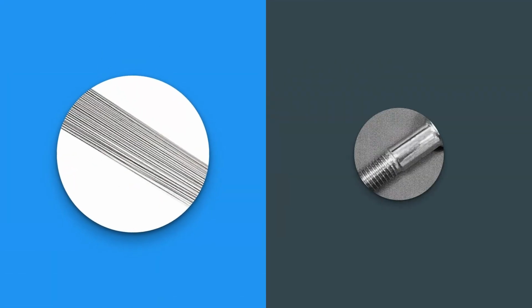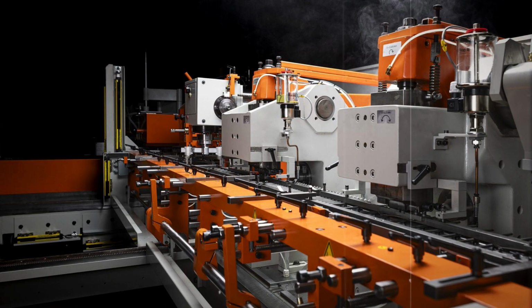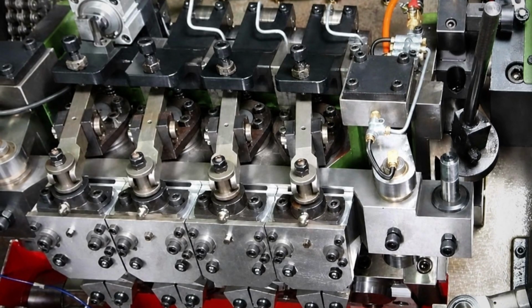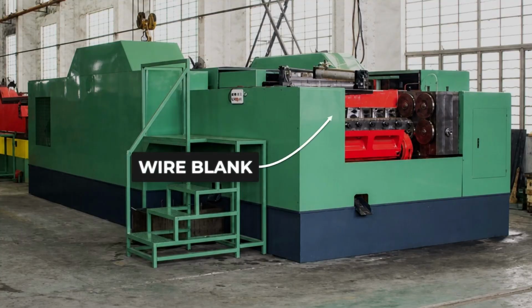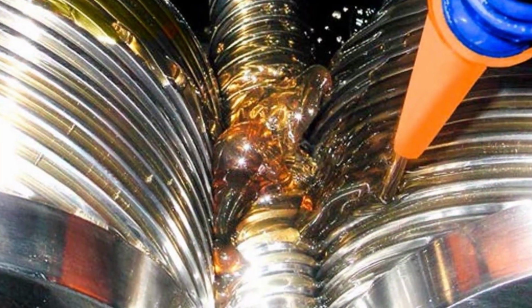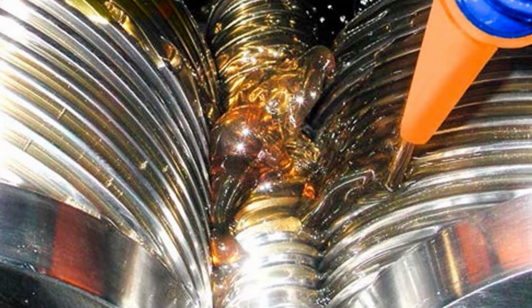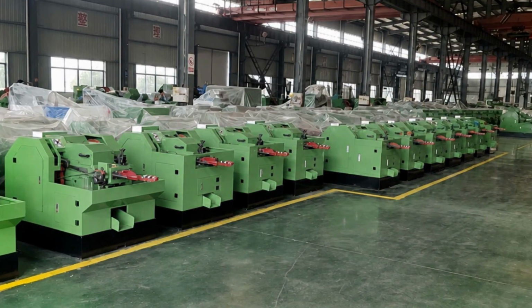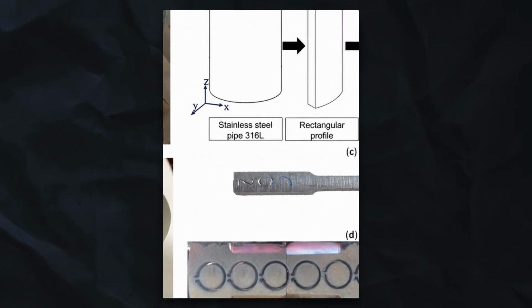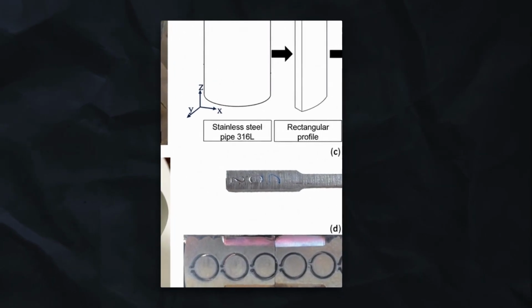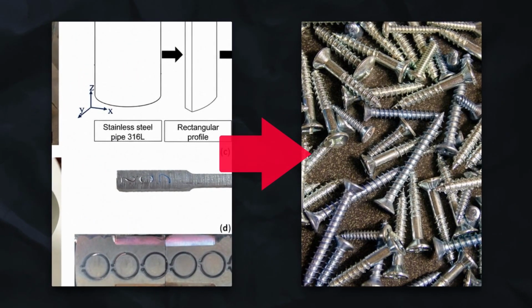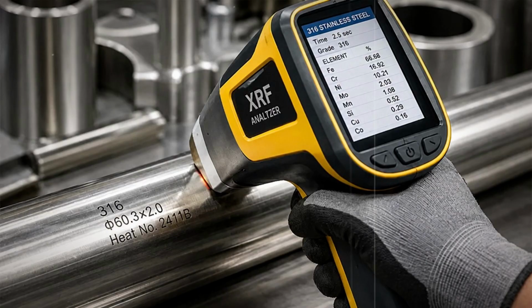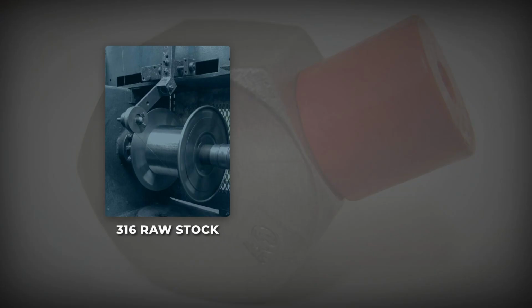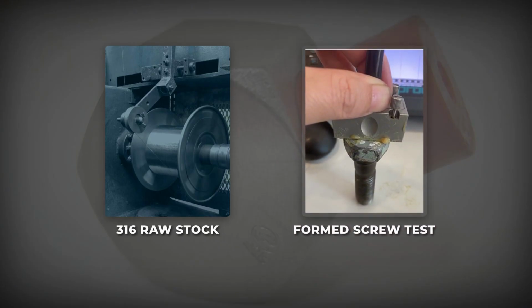A screw is not raw material. Screws are not cast in molds. They are formed by force. A wire blank gets driven into a die to shape the head, then rolled between hardened plates to cut the threads. Both operations push enormous stress into the metal, and that stress rearranges part of the crystal structure of austenitic stainless. The chemistry of the alloy does not change by a single percentage point, and the screw starts answering to a magnet anyway.